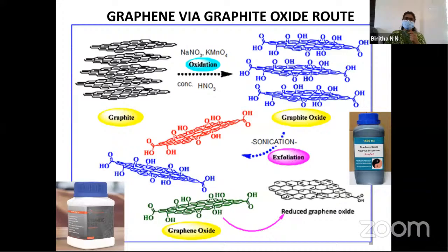In the graphite oxide assisted route, graphite is subjected to drastic oxidizing conditions, and as a result, different functionalities are introduced to graphene sheets, and the layer distance is enhanced. In addition, the hydrophobic graphite becomes hydrophilic graphite oxide. So water can easily penetrate between the layers, and upon sonication, the graphite oxide is converted into graphene oxide. And it is not graphene, it is simply graphene oxide. So after reduction, it is converted into reduced graphene oxide.